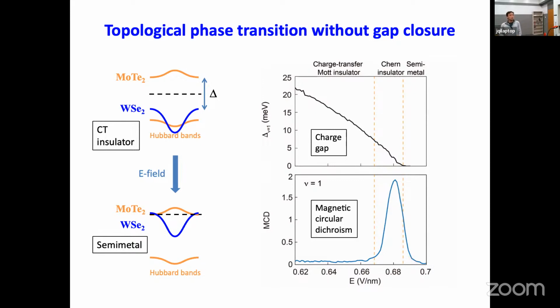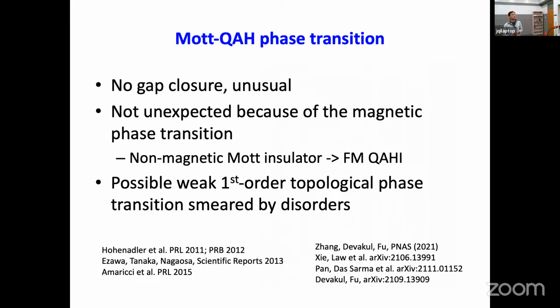a semi-metal. But the punchline here is that when the system goes from topologically trivial, which is a charge transfer insulator, to a topologically non-trivial state, which is a Chern insulator, there's no charge gap closure in this topological phase transition. The Chern number is changed from 0 to 1, but the charge gap actually does not close in this topological phase transition. It just gets closed at the higher electric field when the system turns to a semi-metal without time reversal symmetry breaking. So at the state with time reversal symmetry breaking, there's no charge gap closure. And that's sort of odd because most of the topological transitions that we know.